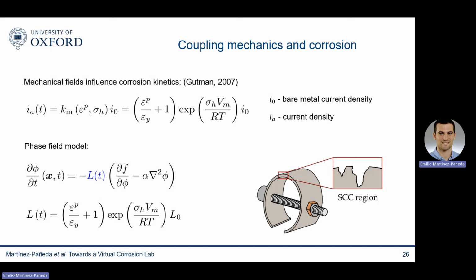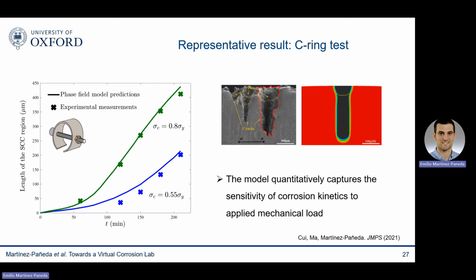And we will test the outputs of this model by comparing against experiments where you apply a constant load and measure the degree of corrosion. Here you can see the results. As you can see, the model delivers an excellent agreement with experiments over 2 levels of applied load for both the degree of corrosion, but also for the morphology of the corrosion defect. You can see it here. These 2 figures have the same scale, and there are multiple pits here. We choose to model only the main pit. We could have modeled multiple pits, and you can see that there's a relatively good agreement.